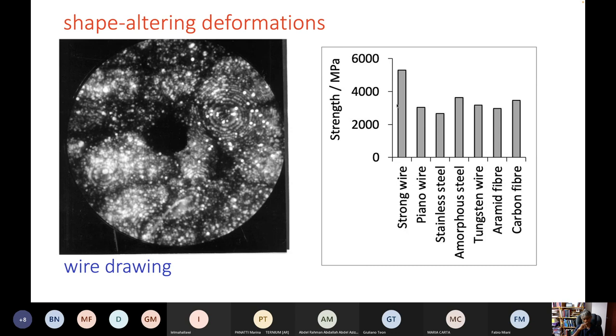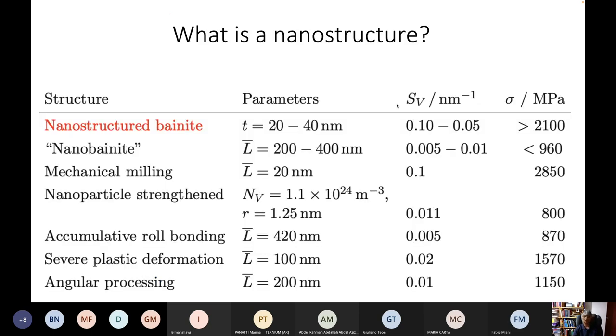Now the word nanostructure — I haven't defined it as yet. What do we mean by nanostructure? At one point there was a lot of funding for research in this area and people were just calling things nano everywhere — we even had a car called the Tata Nano and the nano musical device from Apple. I will talk about nanostructured bainite later, but the length scale — the size of the coherent domains — is of the order of 20 to 40 nanometers, which means that there is a huge amount of surface interface per unit volume: about 100 million square meters per cubic meter of interfacial area.